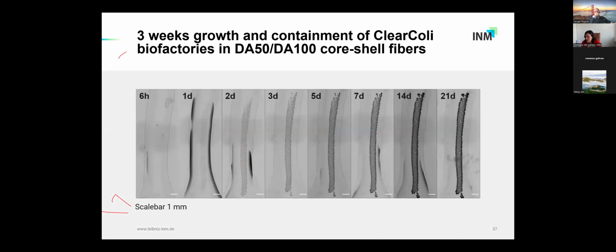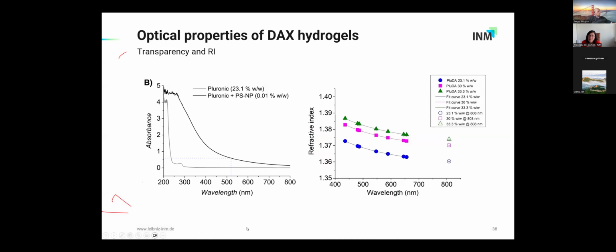In this polymer, also bacteria grow inside, they grow for a long time. If we print the device correctly, we can keep bacteria growing inside for a long time without seeing any leakage. And the pluronic is not only a good material for printing, it's also optical. It's a hydrogel with good optical properties, at least for exposure inside the body. It is transparent or can be transparent depending on the formulation at visible wavelength, and you can tune the refractive index by the solid content of the polymer. So that allows you also to make core shell fibers in which you get the maximum total internal reflection.